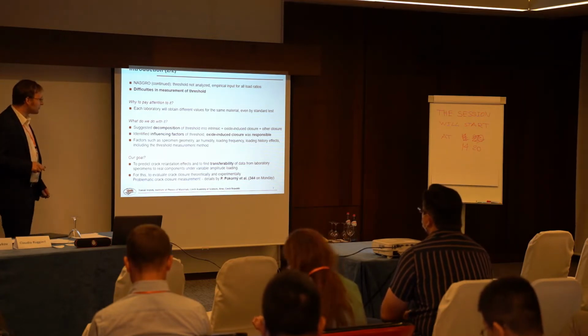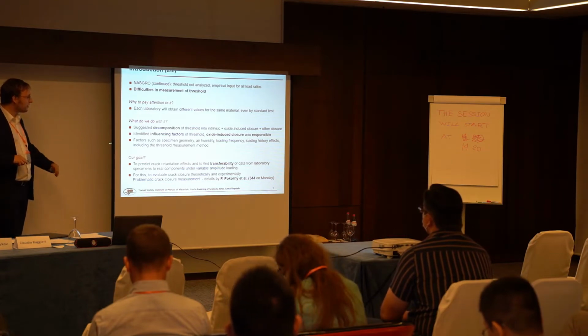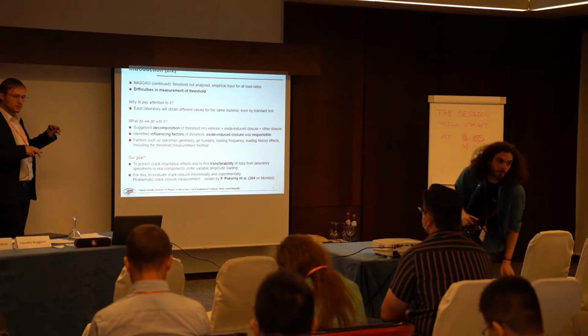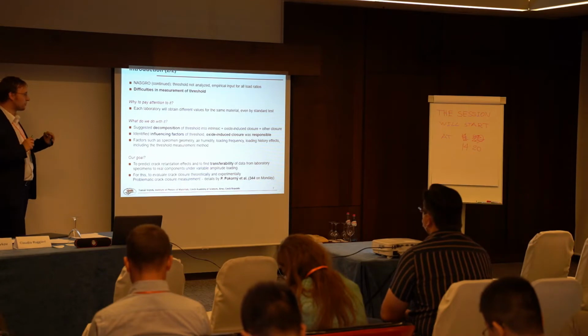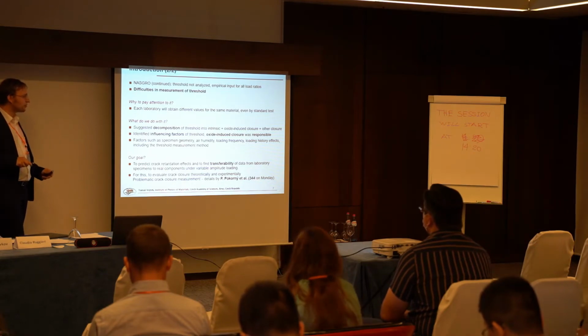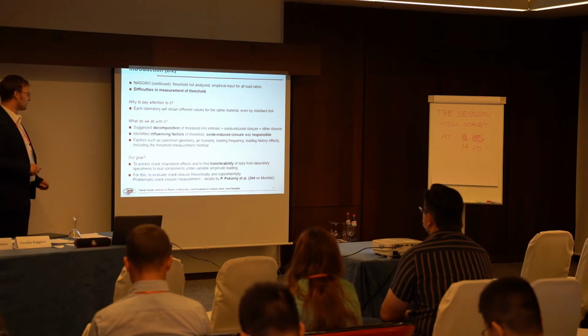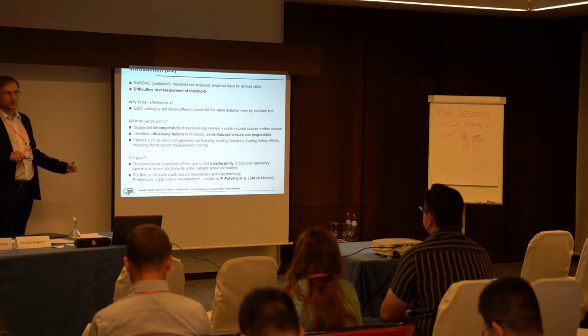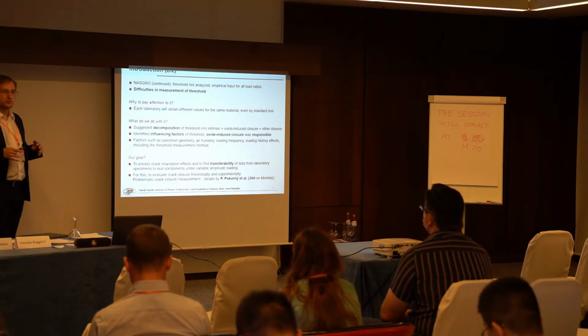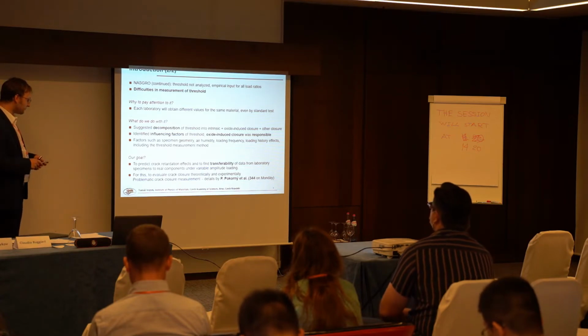And the influencing factors, there can be specimen type, specimen thickness, or even width, humidity, loading frequency, loading history, or the method for the measurement. And we also want to incorporate the knowledge to predict crack propagation in variable amplitude loading, because also due to oxide-induced crack closure, we have some load interaction effects.